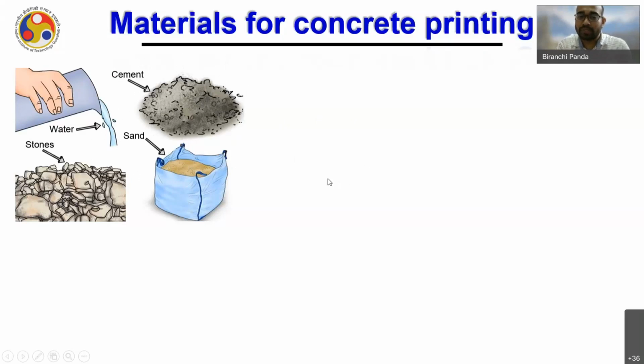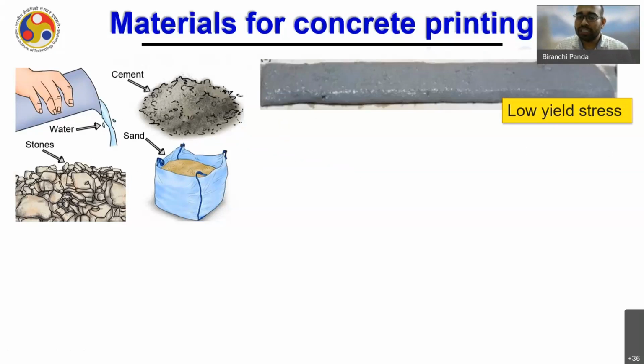If you see the process very carefully, it is very clear that we have to first pump the material to the nozzle. During this pumping process, the material has to be very flowable. Otherwise, it is very difficult to pump such concrete to the nozzle. So if you want to create a pumpable mix, the viscosity of the material should be as low as possible.